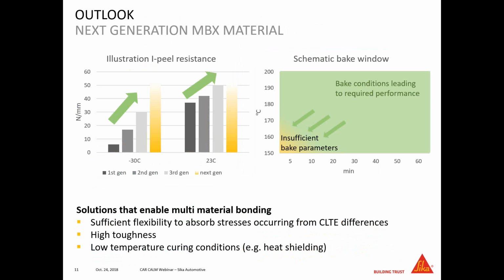So the next generation MBX material will certainly continue to be way more tough compared to the initial materials. On the left side here on this slide, you see that with every generation that was developed, the impact peel resistance, which is a measure for toughness and crash resistance, was increased. And with the latest generations, we came very close also with the low temperature values to the room temperature values. So that difference between the two test temperatures became smaller and smaller. But with the next generation materials, there will be an even higher increase in the toughness, and that's certainly very, very important also for these type of adhesives.